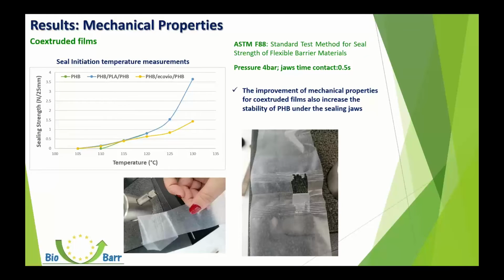The fragile behavior of PHB also influences its behavior during the sealing. In fact, the material is too fragile, and it can have a fragile breakage under the sealing jaws. Instead, in the case of co-extruded films, in which the behavior changes from fragile to plastic, it's possible to observe by the measurement of seal initiation temperature that the material can resist under the sealing jaws, and also the range in which the material is sealable is bigger.